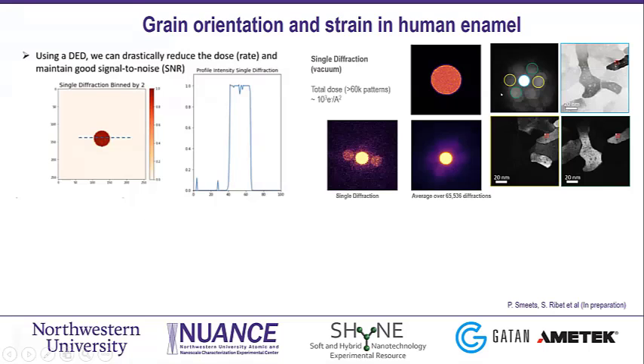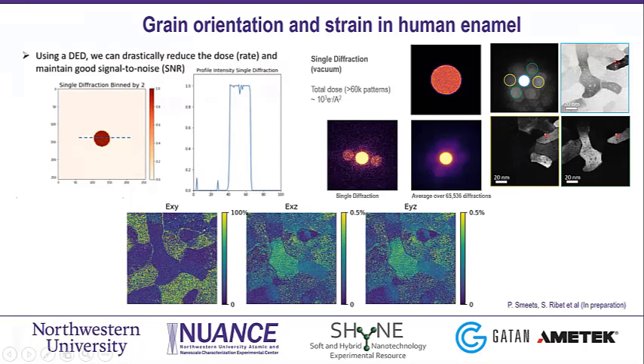So this is from the same work with help from Stephanie here that shows that with that level of signal to noise, you can do virtual imaging like I showed in the beginning, and it can even go further by calculating the strain map, like in-plane and out-of-plane strains here from the diffraction patterns.